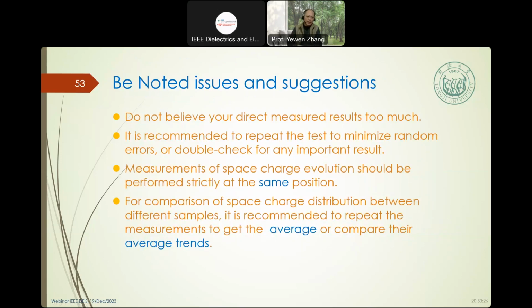So it gives us some noted insulation issues and suggestions. Do not believe your direct measurement result too much. It's recommended to repeat the test to minimize the random error, or double check any important result. The measurement of space charge evolution should be performed strictly at the same position. It's important. For the comparison of space charge distribution between different samples, it's recommended to repeat the result to get the average or compare their average trend. So you cannot measure it one by one. It needs averaging.